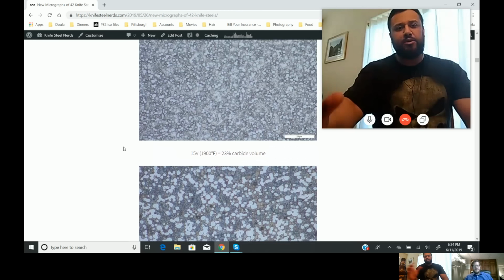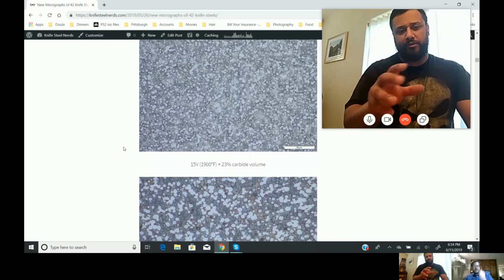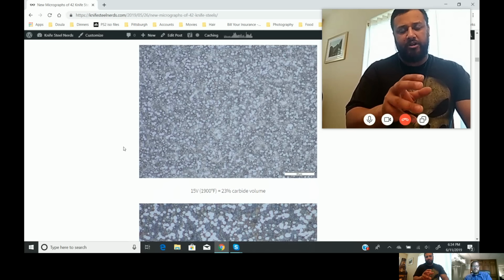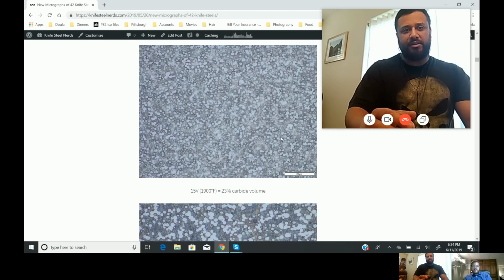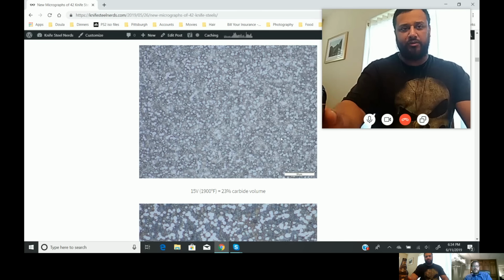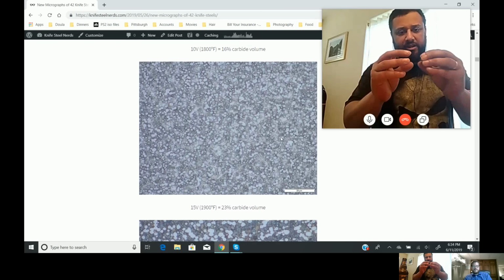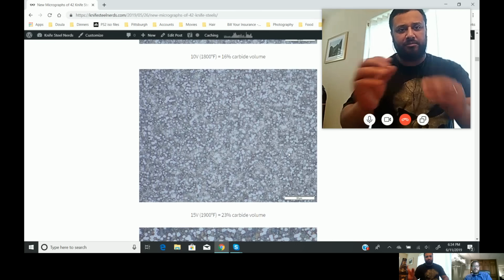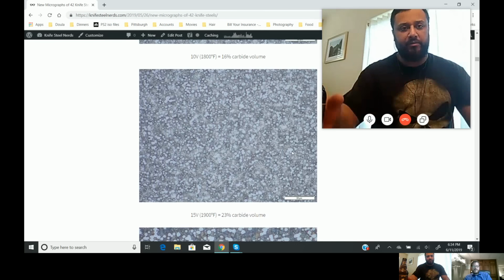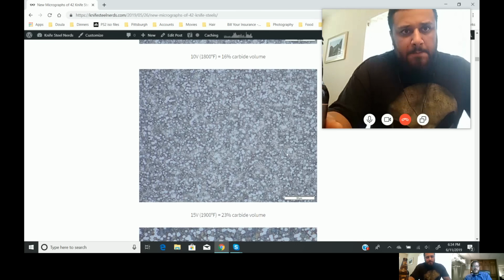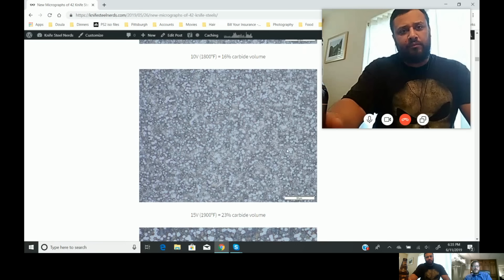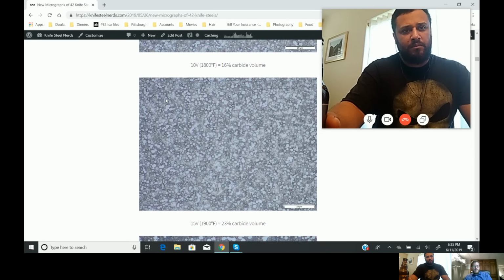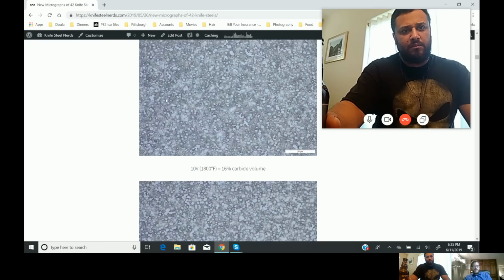That is fascinating. If we look closely at the 15V, while those carbides are finer, there are some areas where they are clumping versus 10V. We could see that doesn't necessarily have that issue. So while the carbides are fine, they segregate into little blobs that you can consider a little bit bigger. Yeah, so I'm pointing to one right here. Even though you can see, like you said, some outlines of smaller carbides, when they're all joined together, they are going to act like a bigger carbide. So here's another example of one right here. And so as you get more and more carbides, they get bigger, even in powder metallurgy.